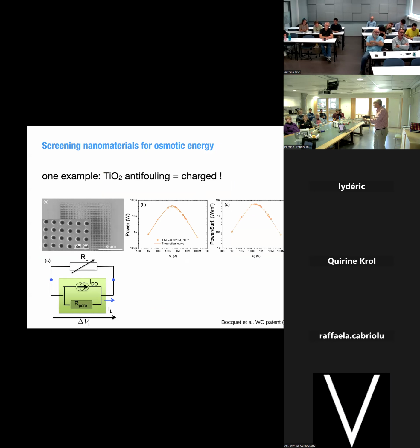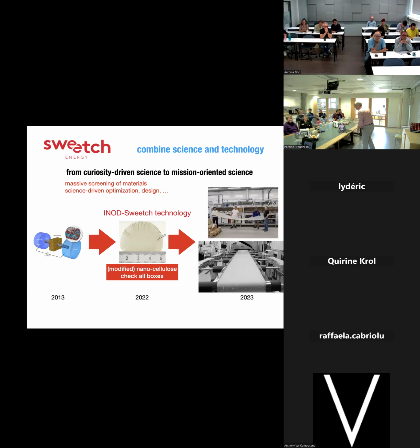So I showed you carbon, activated carbon. For example, we looked also at titanium dioxide, which is very interesting because it's an anti-fouling system. For example, Saint-Gobain has windows which are anti-fouling, and they put titanium dioxide. And usually anti-fouling means large surface charge, because the biological entities don't like high surface charge. So titanium dioxide was working very nicely again. But we tried many aspects, and then I will make a huge jump.